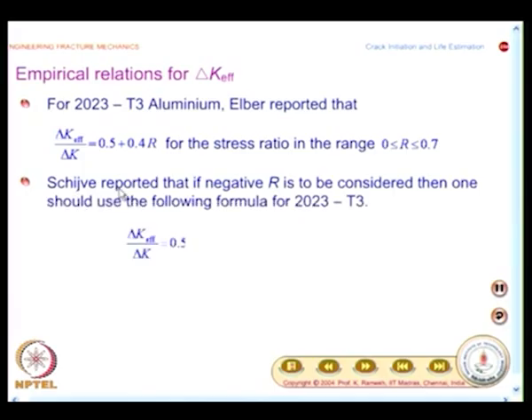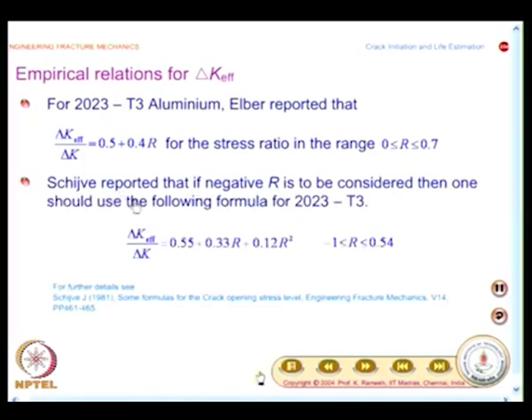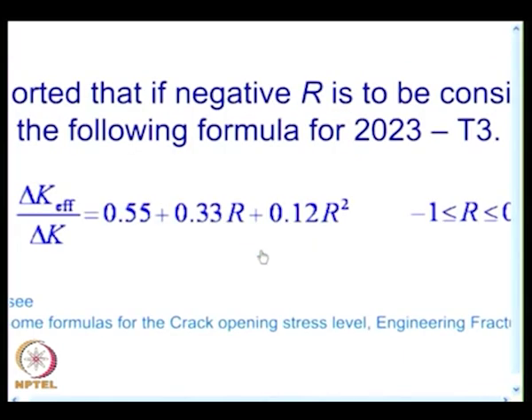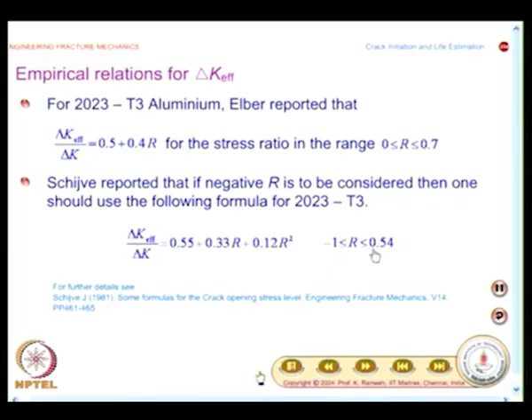And another researcher reported that if negative R is to be considered, then one should use the following formula for the same alloy. This is a little more elaborate, we will also have a look at it, but you can write the expression delta K effective divided by delta K equal to 0.55 plus 0.33 R plus 0.12 R squared. This is for R between -1 and 0.54. For other ranges, you have another expression. See, the point here to note is you have empirical relations available. So, look at the literature, find out for your given alloy what is the empirical relation to use, then you will be able to use